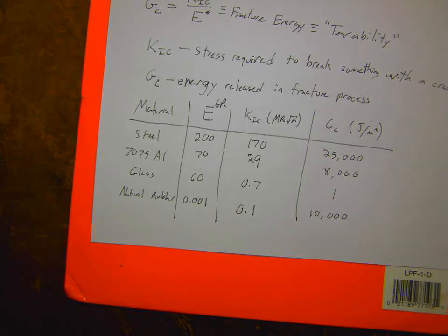And if we look back at that plot of fracture toughness, these are the KIC versus the GC lines. You see for a very stiff material, the KIC can be high even if it's an intrinsically brittle material. Like for a ceramic, because it's so stiff, it has a high stress required to cause fracture to propagate. But if you normalize that by your Young's modulus, you get those ISO lines, those GC lines, and you can see that our rubbers are on the same order of magnitude as steel or as metals, and ceramics have a much lower GC than these other materials because they fall a few orders of magnitude down those ISO lines. Cool.